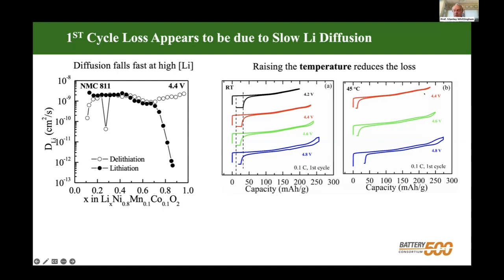So now look at how much capacity we get if we go to 45 degrees from room temperature. And this is 4.4 volts. You see much higher capacity. The first cycle loss is much reduced, clearly indicating diffusion. You see now at 4.6 volts, we're getting a spread of charge and discharge, showing we're getting reaction with the electrolyte. So as soon as you go higher in temperature, the electrolyte is becoming less stable. So we have to find ways of stabilizing this lattice.